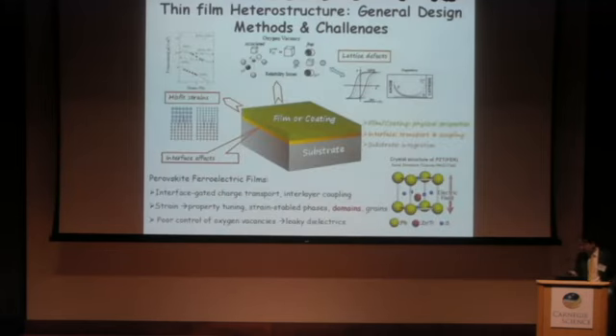So here's the film that you grow on a substrate. Obviously, you need a substrate to support it and also for integration purposes. And you will have an interface between the film and substrate. The film is strained by the substrate, so you're going to have strain effects. And also the film usually has some defects. For example, for perovskites, oxygen vacancy is probably the most important one.